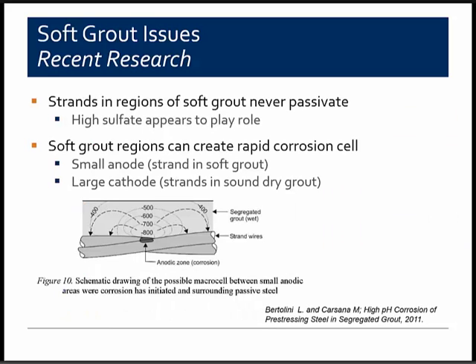Because in terms of the corrosion mechanism, it appears that the portions of the strands or wires within the soft grout material never passivate, potentially as a result of the very high sulfate content and despite the very high pH levels. The lack of passivation and the elevated moisture content of the soft grout material appears to create a very rapid corrosion cell, with the unpassivated strand or the wires that are in the soft grout area at the top of the duct serving as the anode, and they are corroded by all the rest of the strands, the same wires that are all electrically connected together and are down in the dry and hard grout toward the bottom of the duct or away from the high point.